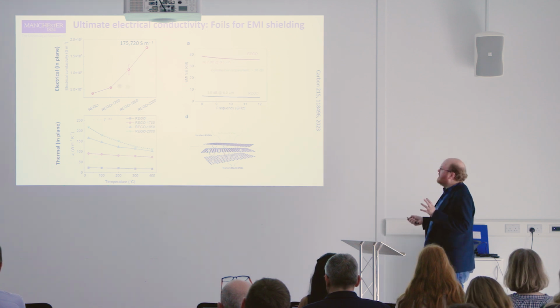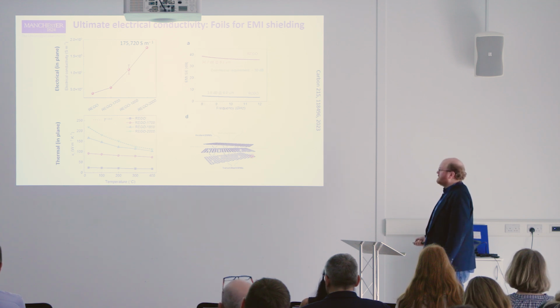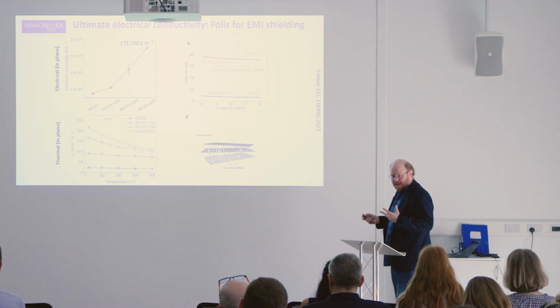But because we've got this electrical conductivity, it's also very good for EMI shielding, because these layers can reflect or dissipate electromagnetic waves. And this is an example of the EMI shielding efficiency versus frequency for graphene oxide or reduced graphene oxide. This is the commercial requirement, around 30, and this is what our material gets, about 36 decibels. This is also thickness dependent, and so we can make these much thinner. This is 8.5 microns thick, which is very thin. It is actually quite close to being competitive with, say, metallized films as well. So again, this single material is an excellent thermal conductor and electrical conductor, and that gives us these multifunctional properties or benefits like EMI shielding, which can be quite nice.